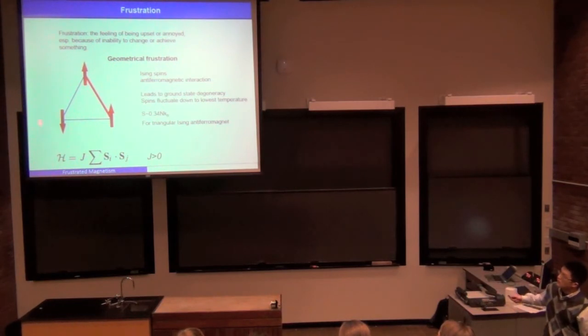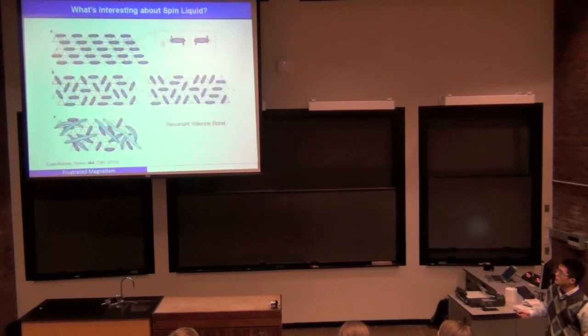For example, for this state, if you flip all the spins by 180 degrees, then the total energy of this triangle is the same. And also we have an unhappy bond here, but in a triangle we have three sides. So the unhappy bond can exist either on this side or on either of the two other sides, and they would cost the same amount of energy. So as a result, we have a ground state degeneracy, which is huge. And because of the ground state degeneracy, the spins can fluctuate down to very low temperature among these degenerate states. This is a typical sign of having frustration in a system.